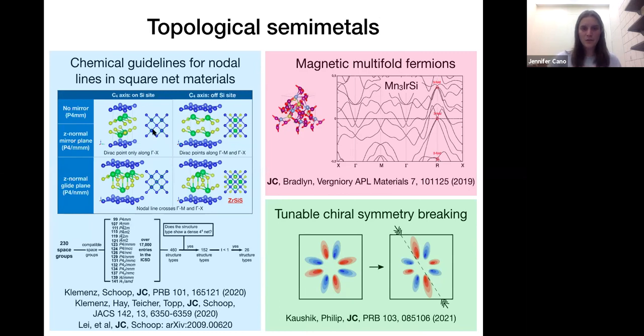You have two atoms in the unit cell, and that gives you a band folding. And it's that band folding that produces these line nodes. And so we investigated different ways that you can stack these different layers. Some are non-symmorphic, some are symmorphic, and they either give you line nodes or Dirac points, but you always get these crossings anyway. And so in this particular class, we were able to deduce it wasn't the non-symmorphic symmetry, it's just the stacking of these square nets.